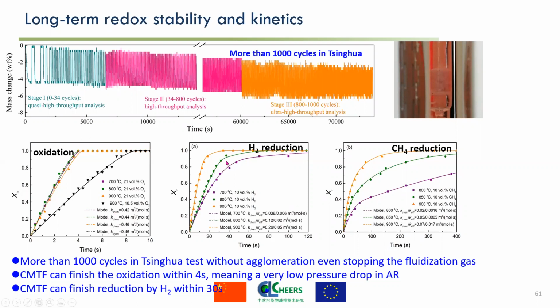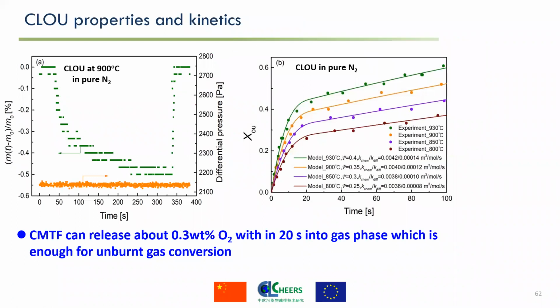You can see CMTF can also be reduced fast by hydrogen. It just needs 30 seconds for full reduction. We also find CMTF can release 0.3wt% oxygen within just 20 seconds. So this oxygen can enhance the gas conversion in the fuel reactor.